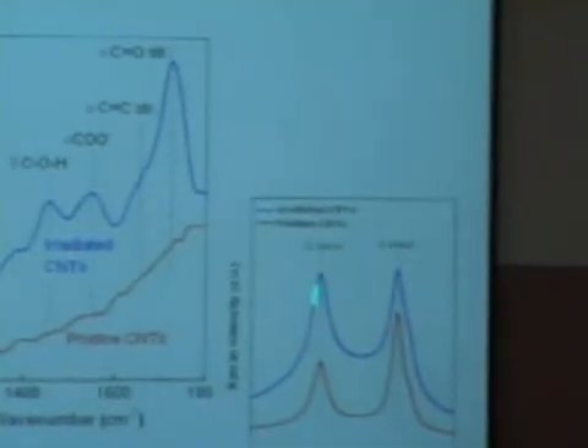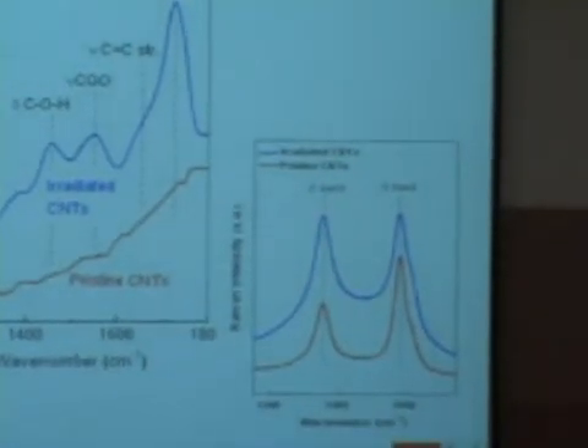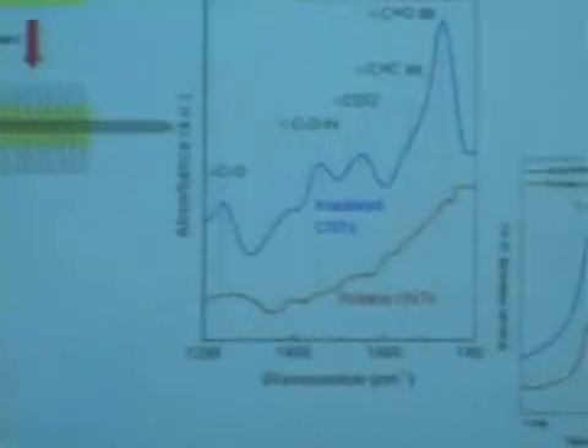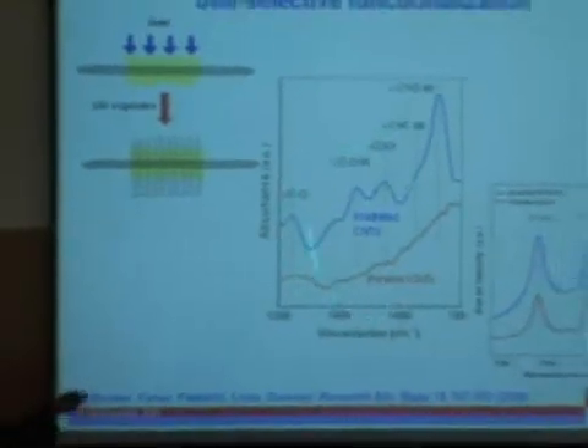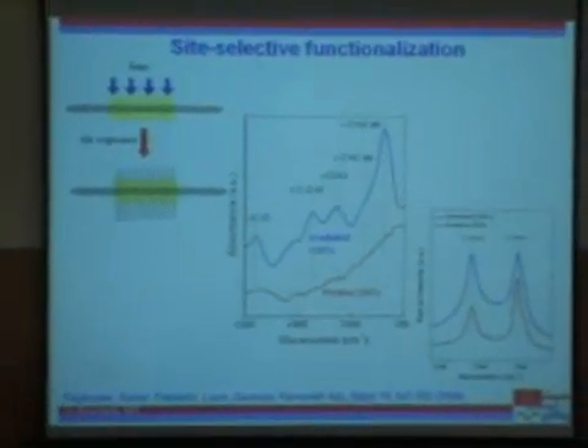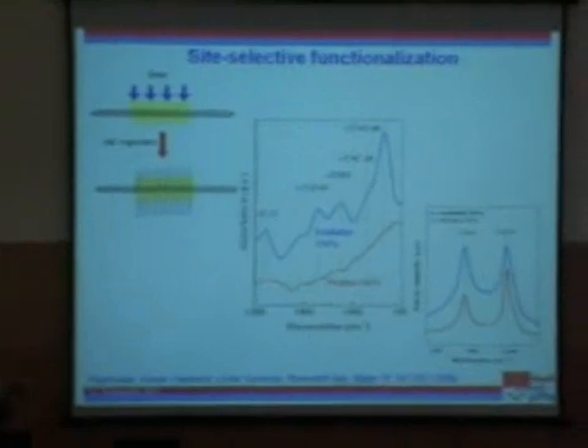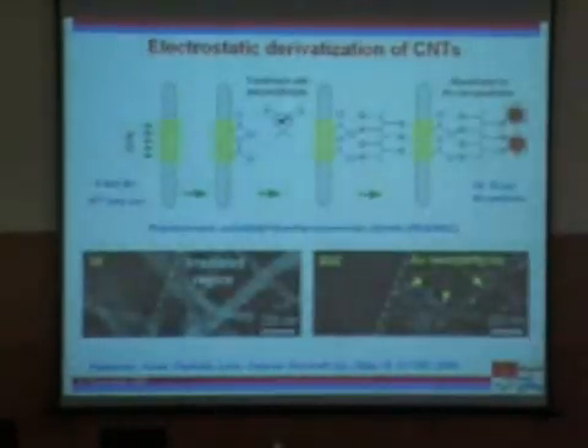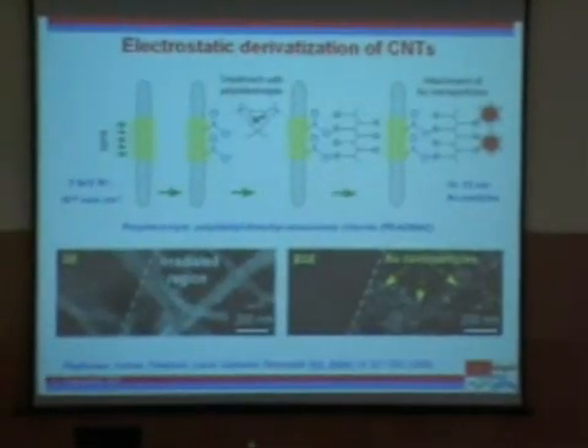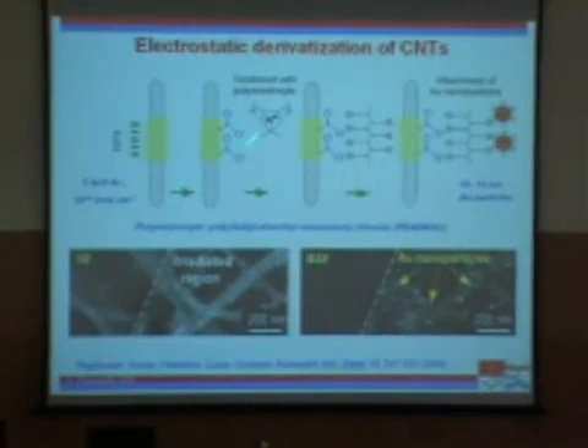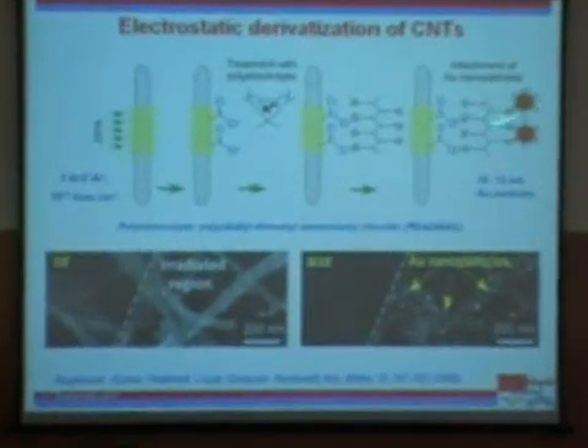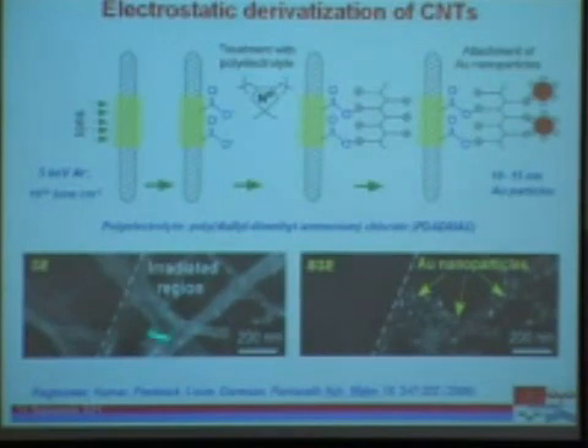And this is Raman spectra, which shows that the D band increases, which means that I'm actually indeed creating defects. So no surprises here, but this is actually the first demonstration of selective functionalization of segments of carbon nanotubes. Okay, and we can do various different kinds of chemistries here. For example, use the carboxyl group and attach gold nanoparticles, and you can see that only the irradiated regions have the gold nanoparticles and others don't.